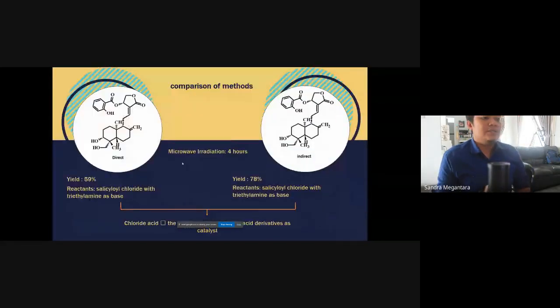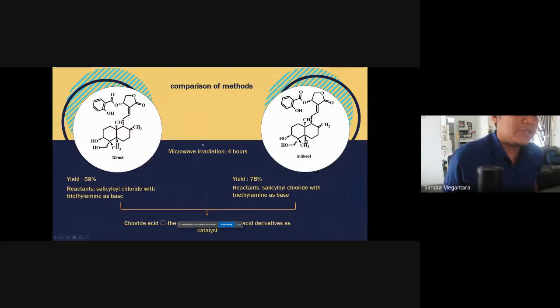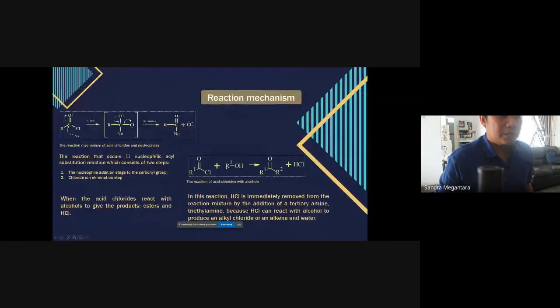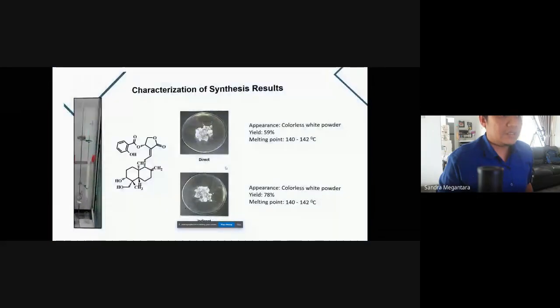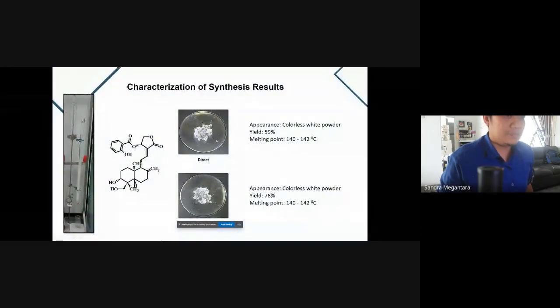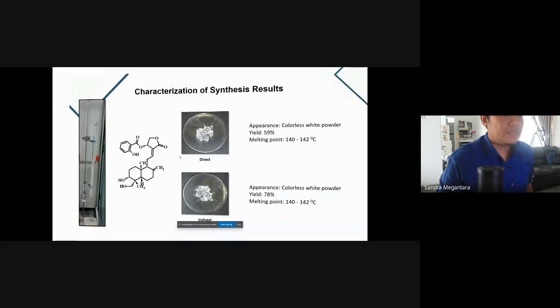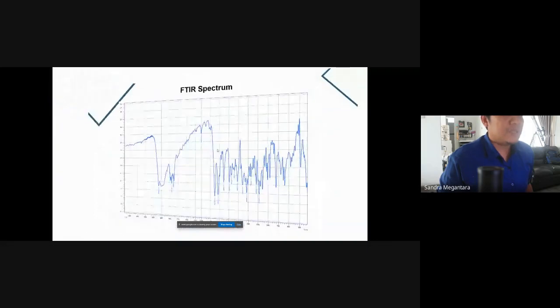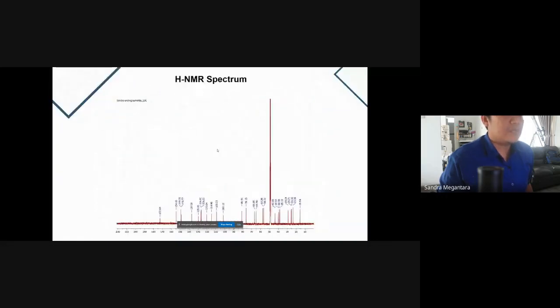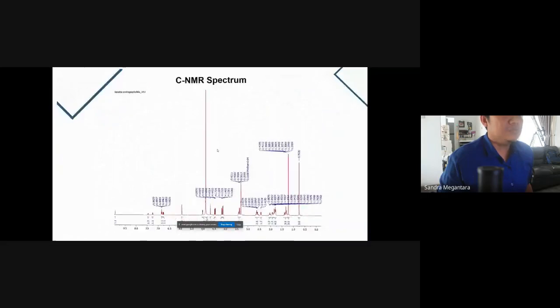And then this is the result, direct method and indirect method. We can see the yield of the indirect method is 78%, which is higher than the direct method with no protection. This is the reaction mechanism, and this is the appearance of our synthesis result. And then this is the FTIR spectrum, MS spectrum, HNMR spectrum, and CNMR spectrum.